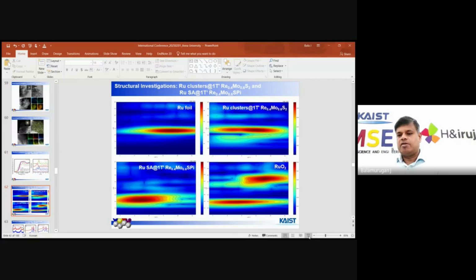So this is also additional confirmation for the single atom versus the cluster. You can see the R value is below 2, not more than 2. From this study, we finally confirmed that our single atom is 100%, but in the case of the foil there are more ruthenium-ruthenium bonds. But here ruthenium is bonded only with non-metallic bonding like sulfur and phosphide. And you can also see the ruthenium oxides. You can see ruthenium-oxygen bonds and ruthenium metal bonding also present. And this is the cluster. In the cluster, the majority is ruthenium metal bonding, and a few ruthenium-sulfur bonds.